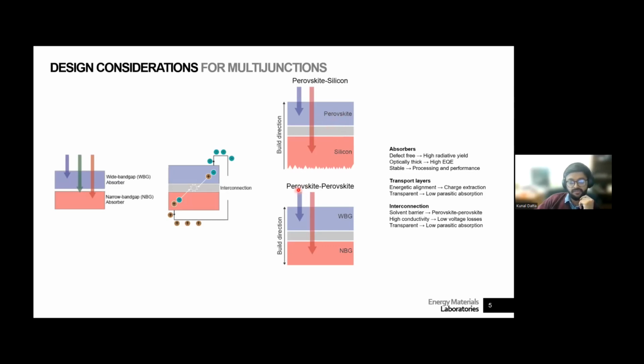In the case of perovskite tandems, you can go in either direction, and typically it's done where you have a wide bandgap solar cell, and then you go and deposit the narrow bandgap cell. So you go this way in the row from top to bottom. The other way is also possible, that you deposit a narrow bandgap solar cell and then deposit a wide bandgap solar cell. There are a few reports recently, especially on that kind of architecture. But the stability of the narrow bandgap solar cell to those kind of processes can be a bit of a restriction, but it's possible in principle and also in practice.